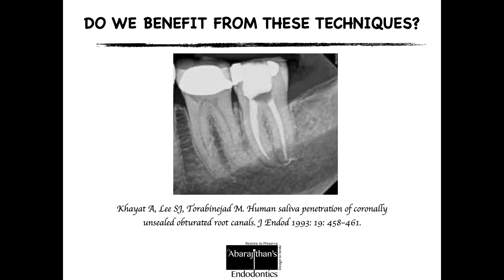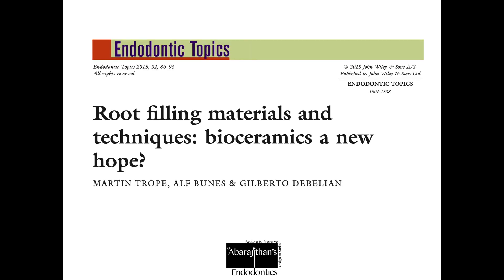But the biggest question is: do we benefit from thermoplastic obturation with traditional sealers? According to one study, the time taken for coronal leakage to reach the apical area is just 30 days once the coronal seal is lost. This means that in spite of achieving high bond strength, the bonding of the sealer to dentin and to gutta-percha is not great - they are not resistant to leakage.